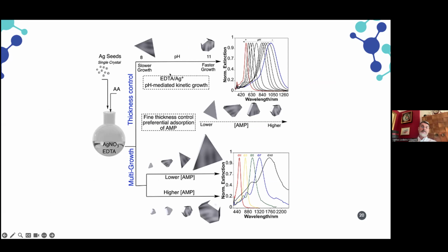So as you can see here, working with the pH between pH 8 and pH 11, the absorption band of the nanoparticle is modulated between 420 and 1,200 nanometers. So this allows you to obtain nanoparticles that are very stable in the near infrared region. But also, if you work with the multi-growth methodology, in which we increase the concentration of the adenosine monophosphate, we can move the plasmon resonance band close to 2000 nanometers.